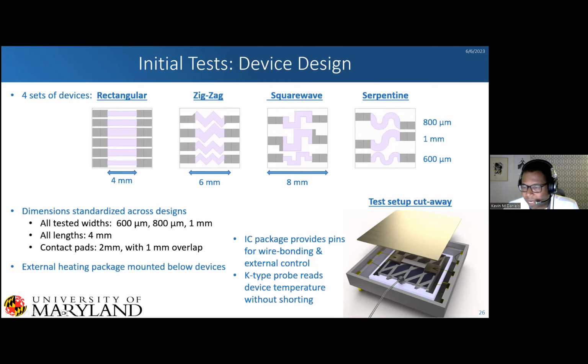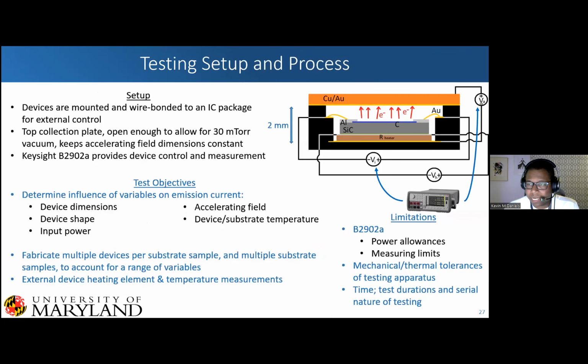This is a 3D mock-up of our device. We have, for example, one ribbon here, and a thermocouple going in here for us to monitor the temperature of our device. This is our testing setup. We have a copper gold plate sitting on top of our package, and we have a potential applied to our graphene ribbons. We have an accelerating field between this plate and our top plate. And all of this was done in a vacuum chamber, again not very high vacuum, around 30 millitorr.